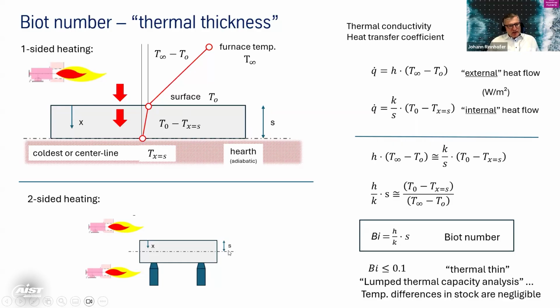And to select S, you have to look at the situation. Do you have one-sided heating only, like it is shown here on the top? So you have an adiabatic line here at the hearth, or you have two-sided heating. Then you have the adiabatic line basically at the center of the slab. So there's no heat transferred over this line. It comes from both ends and meets in the middle. So this is why you have to select S correctly when you look at the Biot number.